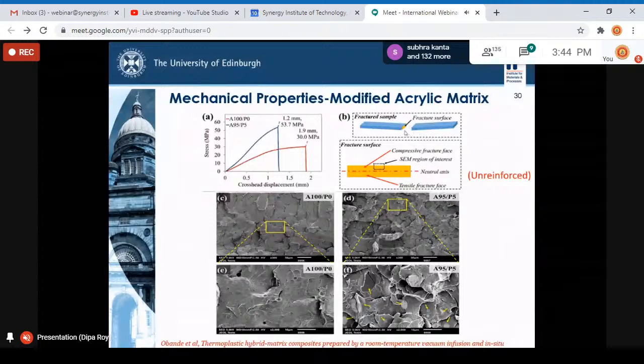This is how we fractured the sample, and in these micrographs we could see some zones of these polyphenylene ether, but the ductility was still there. We can see here the flaky nature of the matrix, which is quite visible in pure acrylic. That was still there in these blends, but at the same time we saw some significant enhancement in the strength or the mechanical behavior of the blends.